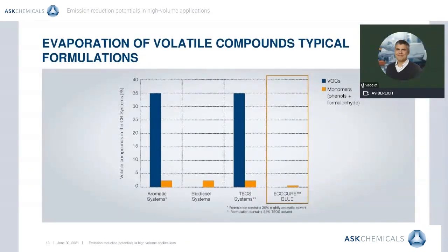So if we look now at the evaporation phenomena, there are already VOC-free formulations on the market, whereas recipes containing aromatics or TEOS generate VOCs. However, phenol, with a vapor pressure of 0.2 hectopascal at 20 degrees, is a pure VOC, and its occupational exposure limit of 2 ppm or 7.8 milligram per cubic meter demonstrates its toxicity. Phenol penetrates the body very easily by inhalation. EcoCure Blue reduced the release of phenol by more than 80% and thus greatly reduced the risk for workers.